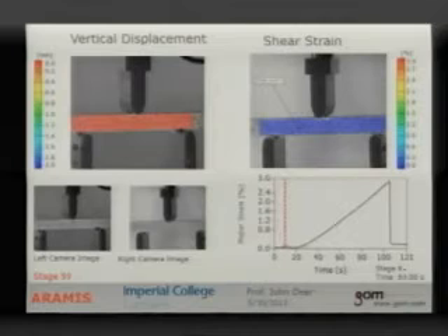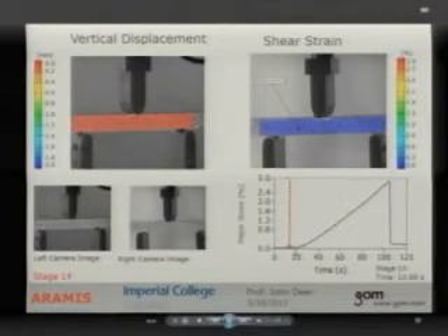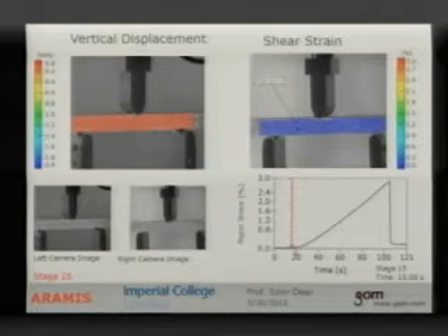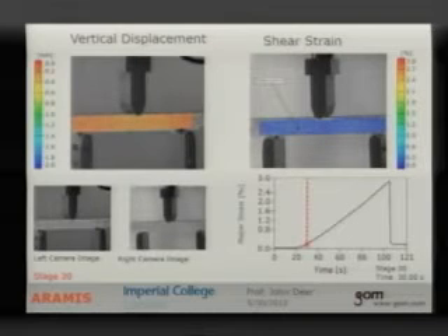So you can see there on the left is the vertical displacement, so it's color keyed, so 0 is red. As it plays now, it should get yellow and green, and you should see a little bit more displacement under the central roller. In the bottom right, you can see the strain at a particular point on the sample, which is going up in a linear fashion. And the right-hand plot is the shear strain.